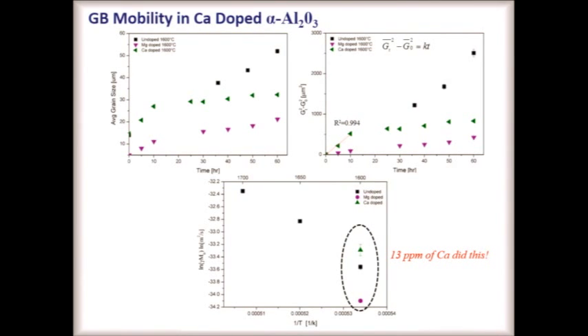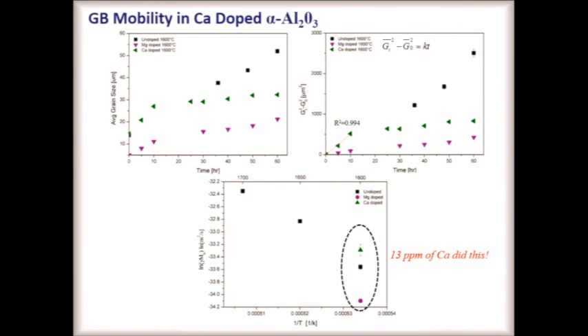So the grain growth goes faster. Grain boundaries move faster with only 13 ppm of calcium. And again, we're significantly below the solubility limit. Calcium is going to the grain boundaries, and it's making the grain boundaries move faster. That's not solute drag. Compared to magnesia or compared to undoped? Both. Okay. Both. This is undoped, this is magnesium, this is calcium, okay?